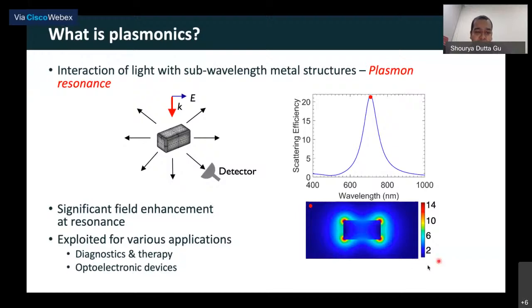So blue basically means a low electric field amplitude. Red actually means a very high electric field amplitude. Now, if you notice around this structure, around this cuboid, at the corners we have very high field enhancement, right? It goes to almost a factor of 14 as compared to the one which is farther away. And this near field is what we exploit for various applications.